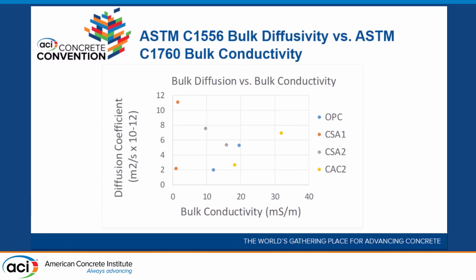But we did the bulk diffusion versus the bulk conductivity, and we can see that in general, when the diffusion drops, the conductivity drops also. What should be noted here, and I think it's alluded to by some of the previous speakers, is that the same conductivity and the same bulk diffusion don't necessarily agree. A different material will have a different relationship.